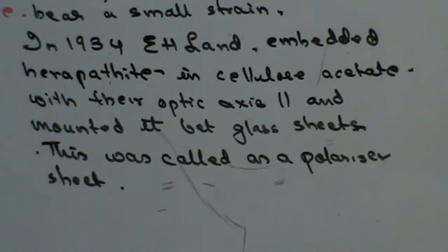So thus you have two different kinds of Polaroids: H Polaroids and K Polaroids. H Polaroids are prepared by stretching a polyvinyl alcohol film between 3 to 8 times under the presence of a large strain. The optic axes automatically arrange themselves parallel to each other, and they are then further impregnated with iodine crystals to make them highly dichroic.